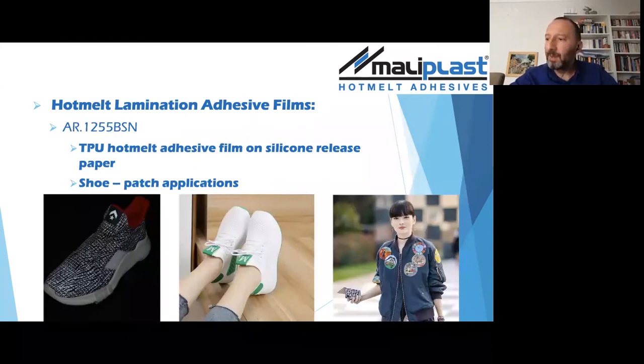On the Hotmelt adhesive film side, we also have two TPU Hotmelt film grades, which we are selling to our customers. The first one is the one which we recommend for shoes. Actually, the new type of Skechers type shoes made directly from knitted fabric, or TPU hot melt film is mostly used there for the lamination of the logos on the shoes, and this product is also used for the lamination of patches. Not actually on the confection side, in order to increase the production speed, in some cases the patches are not sewed, but they are applied with a hot melt adhesive, and TPU hot melt film gives very good performance there.